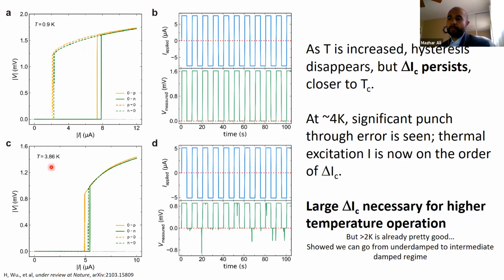But at about 4 Kelvin, so quite a high temperature now, and the important thing is, at this temperature, the hysteresis, you might notice, is almost completely gone. Again, the hysteresis is between a solid line and its corresponding dotted line. The delta IC is between the two solid lines. So you see there's still a delta between the two solid lines, but there's almost no difference between the solid and dotted lines. So the hysteresis is pretty much gone.